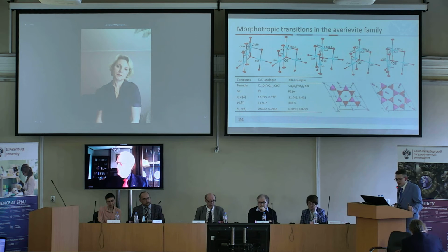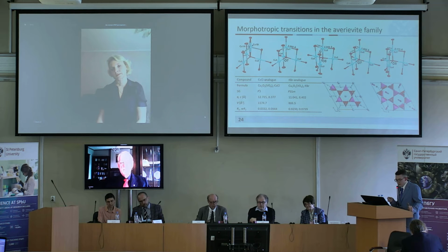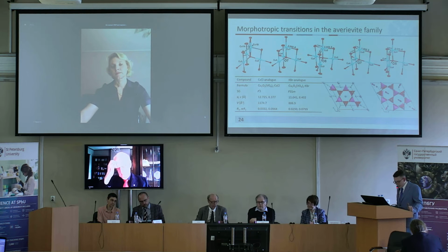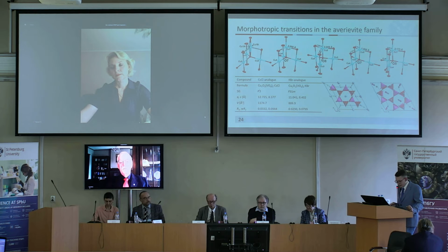At the same time, the cesium chlorine containing phase has a unit cell 4 times bigger, and the potassium bromine containing phase is non-centrosymmetric. In both phases, the alkali metal atoms are relatively ordered, and the halogen ions are located within the layer of oxo-centered tetrahedrons. Apparently, increasing the size of the ion leads to the distortion of the coordination geometries.